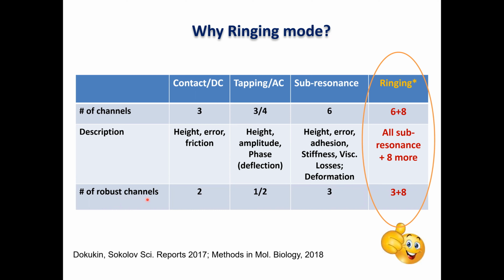What is also important to mention is robustness. Robustness means at least repeatability. You can really repeat from one microscope to another. If you reduce the number of channels to robust channels, for example, the error signal is definitely not a robust channel. It literally depends on how big gains you use, the feedback gains. So it will reduce to 2 for tapping mode, maybe even 1, or total deflection maybe gives you